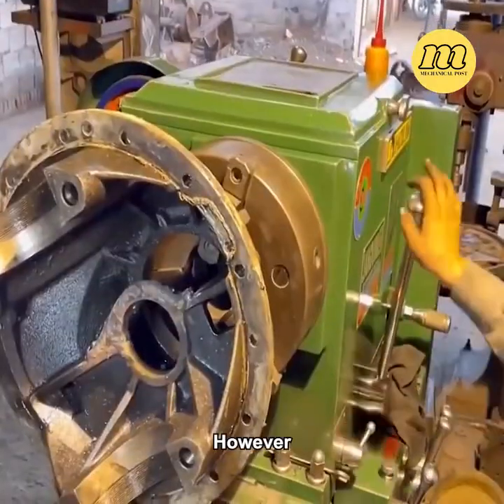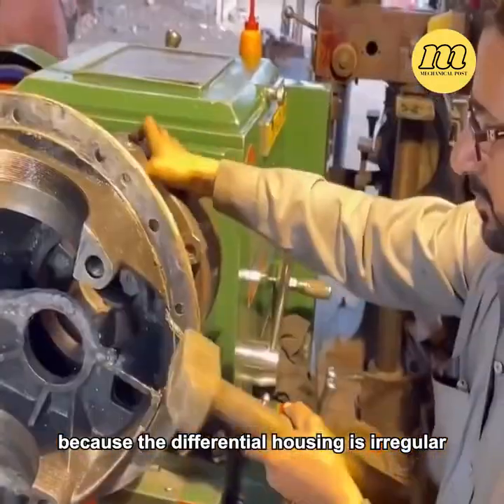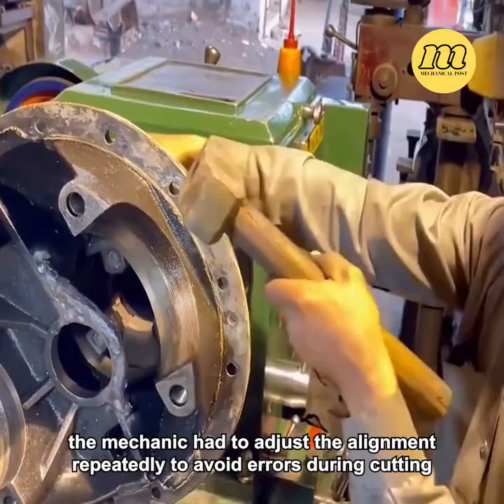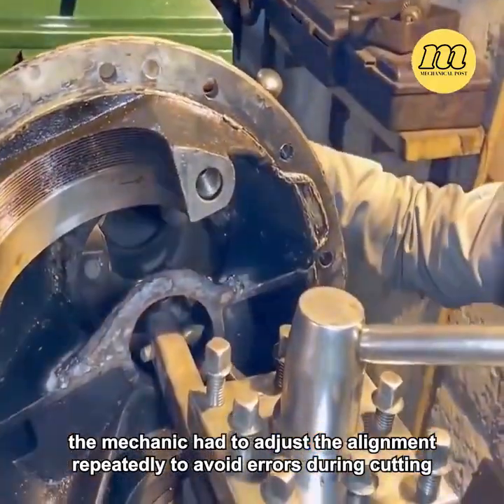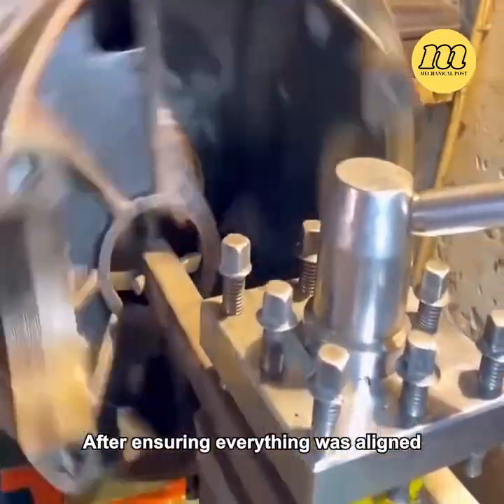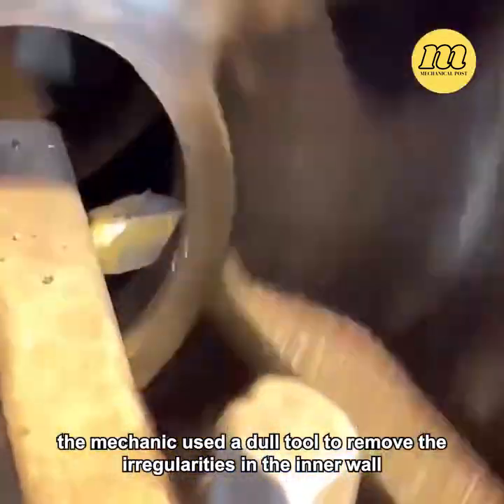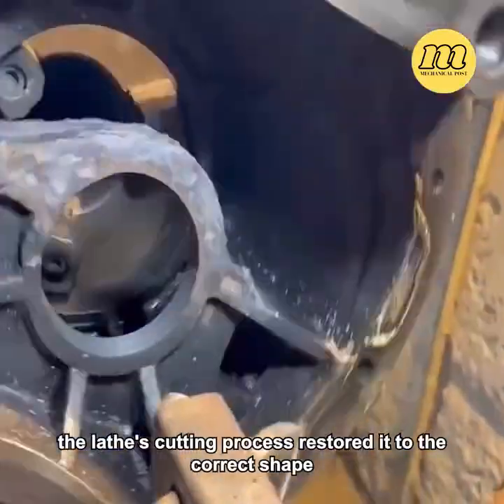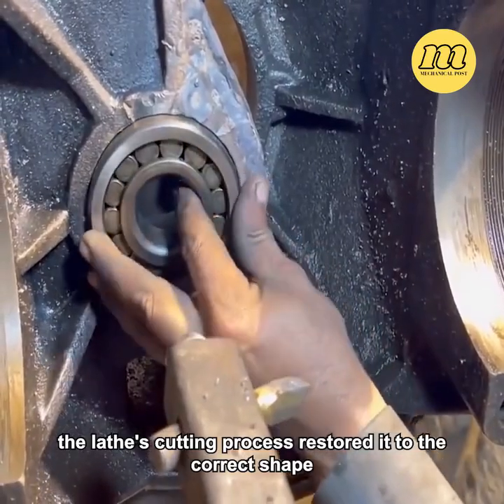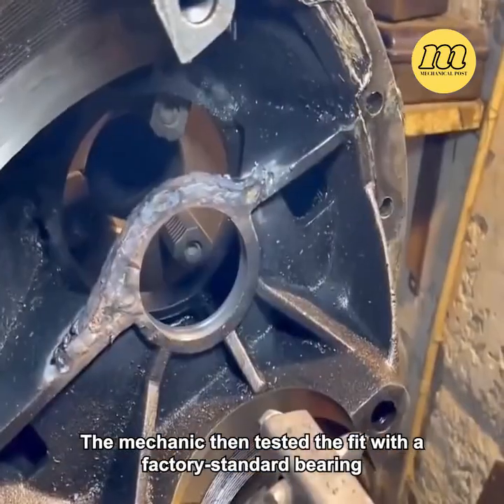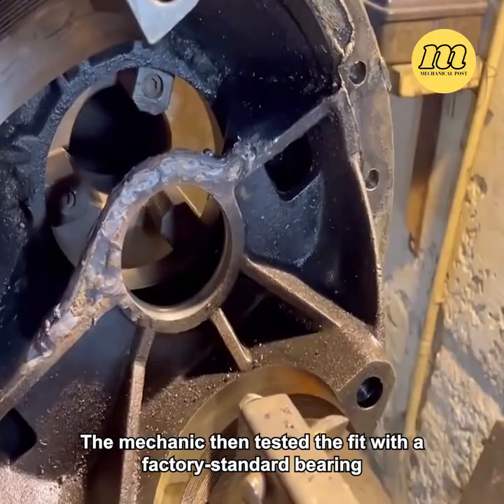However, because the differential housing is irregular, the mechanic had to adjust the alignment repeatedly to avoid errors during cutting. After ensuring everything was aligned, the mechanic used a dull tool to remove the irregularities in the inner wall. Even though the welded inner ring was not perfectly round, the lathe's cutting process restored it to the correct shape. The mechanic then tested the fit with a factory standard bearing.